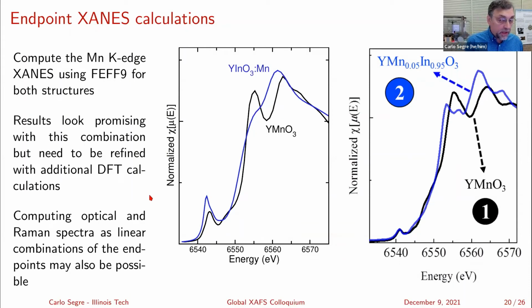What my ultimate goal is, of course, is that once I have the right structure and I can show that's what I have with XANES, I know I can take the results of my DFT calculations and then predict the Raman spectrum. And presumably the optical spectra as well, which is what my real goal is, to be able to predict this mixture of the two different spectra. So that's where I am with the yttrium manganese indium.